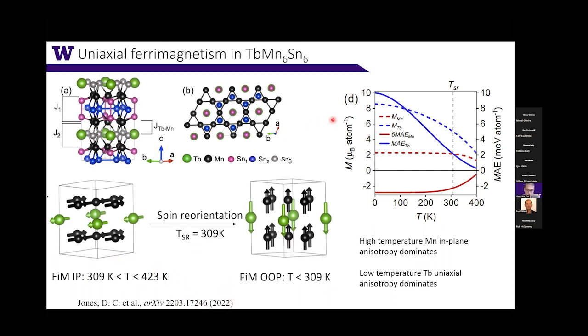So what's going to happen is that at high temperature, when the manganese moments dominate, then you have the in-plane manganese easy plane anisotropy. So therefore, the overall system has an in-plane anisotropy, but as you get into lower temperature, the terbium moments become more dominant, then you have this strong uniaxial anisotropy from the terbium, and therefore the magnetization flips around this 300 kelvins, and then you have this spin reorientation transition.